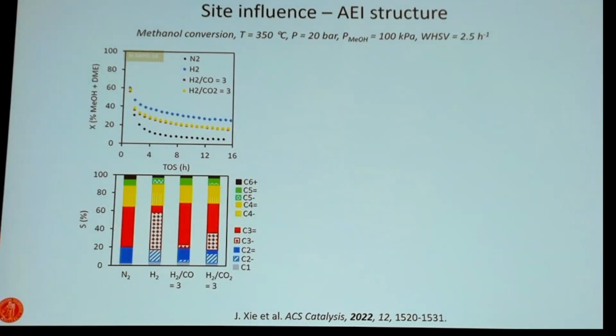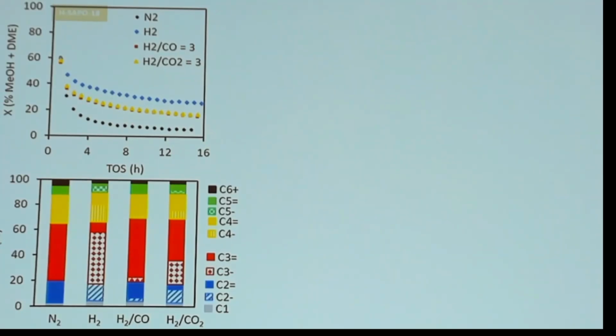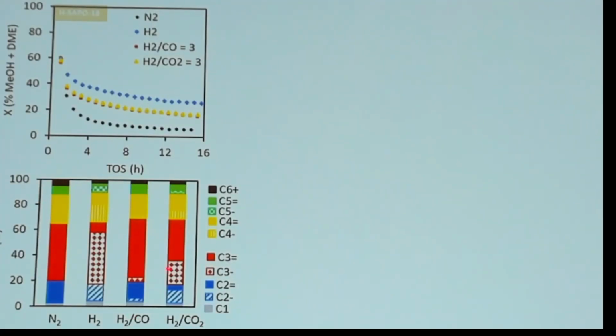Next we look at something that was very exciting to us. When we look into the product distribution, we have the C2, C3, C4, C5 plus, and then this is C5 and C6 plus. These are mainly olefins when we don't have any co-feed. When we co-feed hydrogen, you see the patterned part here, those are the saturated products. And then when we co-feed CO with hydrogen, we see that CO actually suppresses the hydrogenation of olefins. This is, of course, very important when we want to develop a process for making propylene. We see that with CO2 co-fed, there is also somewhat of a suppression, but that is because the hydrogen pressure was lower. We have verified that with other experiments.